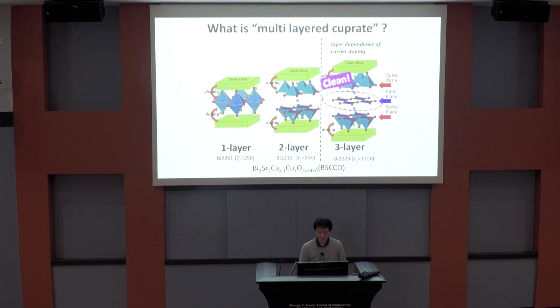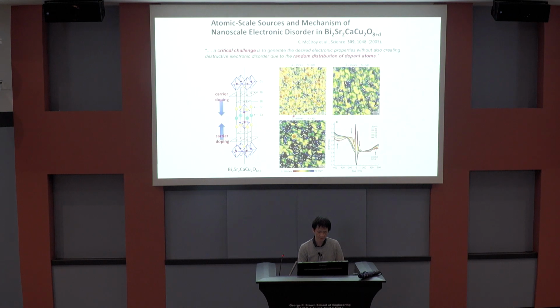As I said, another property of the multi-layer system is that the inner layer is very clean because it's far from the dopant layer. A famous feature of cuprate is the inhomogeneous gap state in real space, which is mostly coming from disorder induced by the adjacent dopant layer.